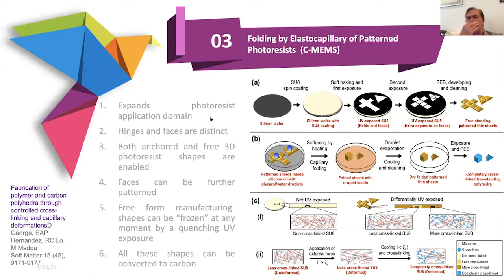With the first remark, what do I mean here? Well, photoresist so far has typically been used in 2D, in 2 dimensions. What I'm doing here is truly make 3D shapes. The hinges and faces are now very distinct. I can easily make anchored and free 3D photoresist shapes. To leave it anchored, I just make it such that the material underneath forms a good adhesion, and has a sacrificial layer underneath those faces that I want to lift out of the surface.